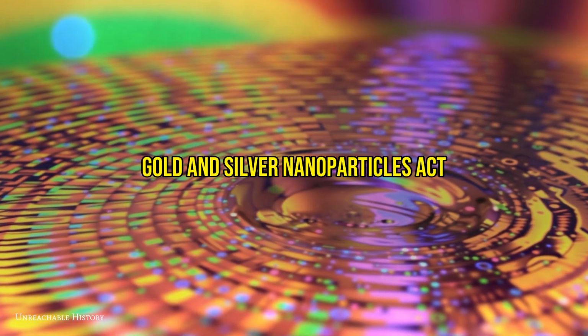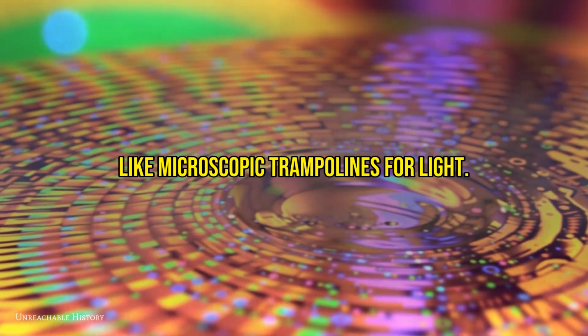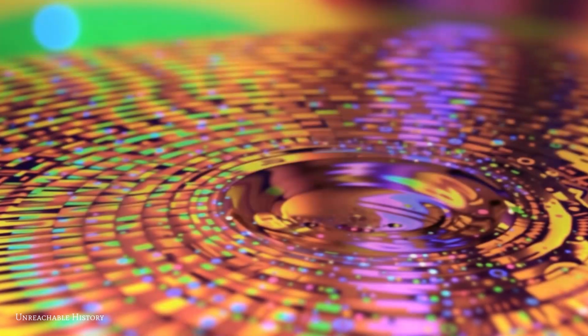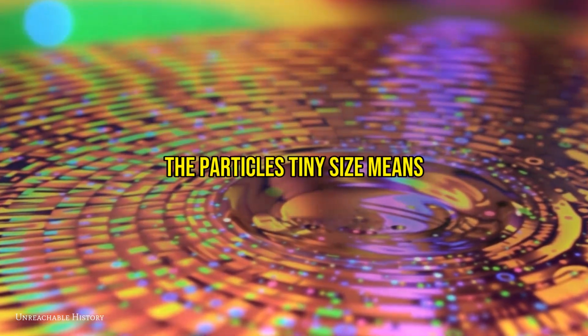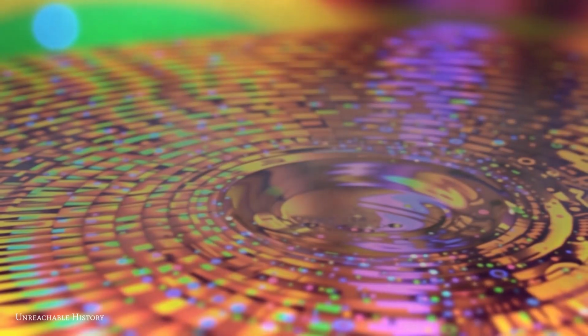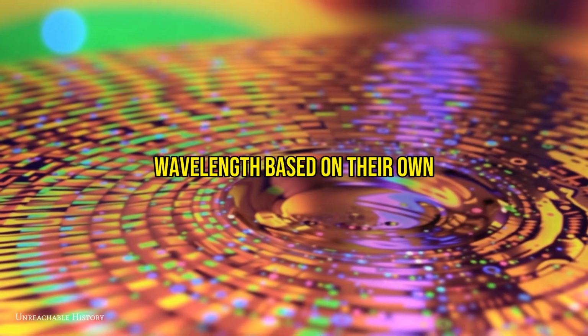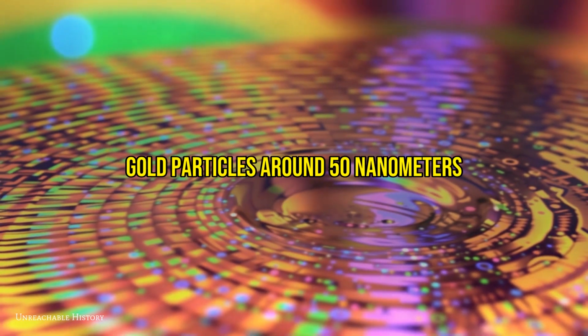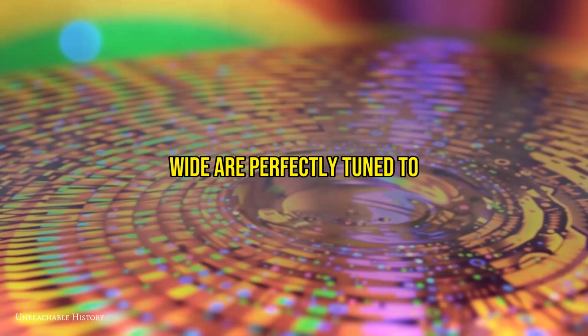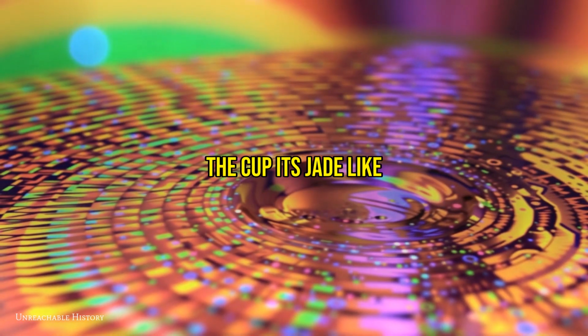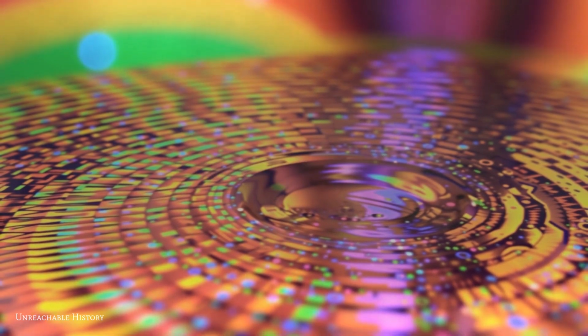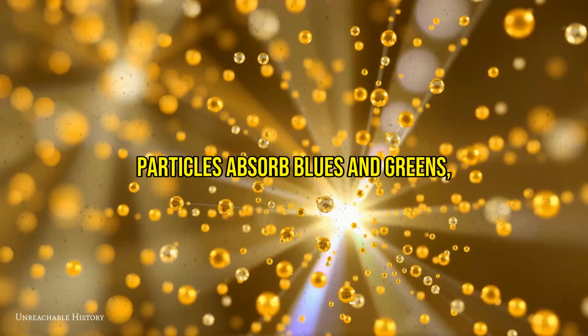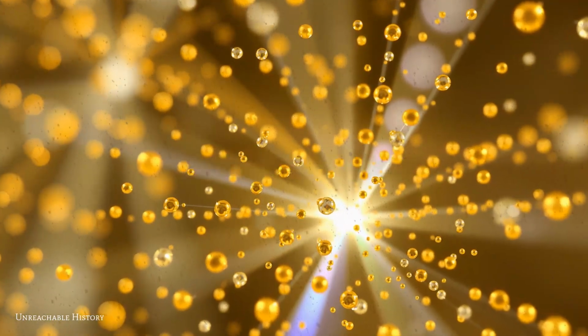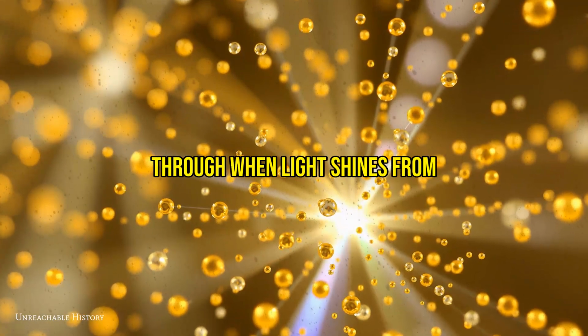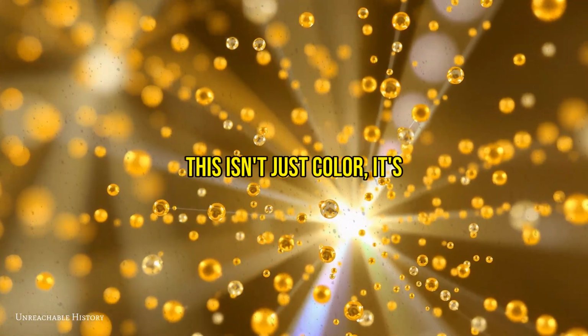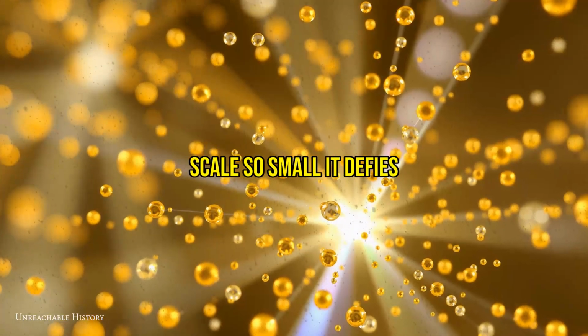The gold and silver nanoparticles act like microscopic trampolines for light. When white light, a mix of all colors, strikes them, the particles' tiny size means they can't absorb all that energy evenly. Instead, they selectively scatter specific wavelengths based on their own dimensions. Gold particles around 50 nanometers wide are perfectly tuned to bounce back green light, giving the cup its jade-like glow in reflected light. Meanwhile, the slightly larger silver particles absorb blues and greens, acting like a filter that only lets red wavelengths pass through when light shines from behind. This isn't just color, it's physics playing out at a scale so small it defies intuition.